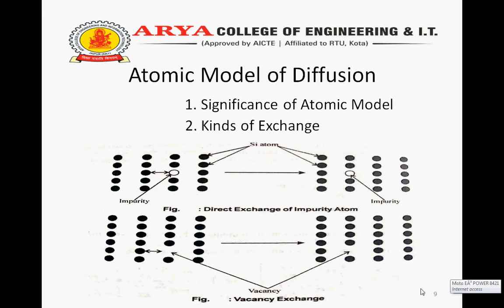If we insert an impurity atom into the crystal, the atom wanders between lattice site and interstitial position. The atom may also substitute the silicon atom in a lattice site. Second is a kind of exchange. There are two kinds of exchange according to the atomic diffusion model. First is direct exchange, second is vacancy exchange. In direct exchange, at least 6 bonds must be broken, while in vacancy exchange only 3 bonds must be broken. So vacancy exchange is preferred for substitutional impurity.